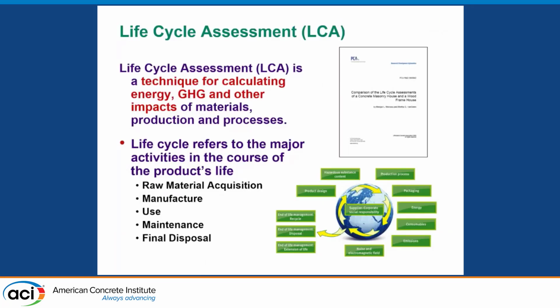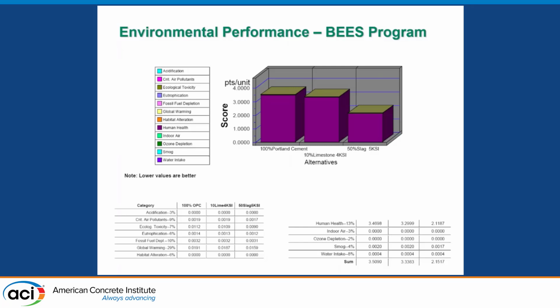But certainly by looking at life cycle assessment, which I talked about earlier, we can really see, if we start going to blends, that we can reduce raw material acquisition. We can also reduce some of the manufacturing. Maintenance and disposal will go down as well. So maintenance costs are extremely reduced when you start having proper service life. And certainly when we look at the environmental performance, this looks at just the difference between a Portland cement, 10% limestone at a 4,000 psi mix, and if we use 50% slag. So we can see there's a different environmental score.